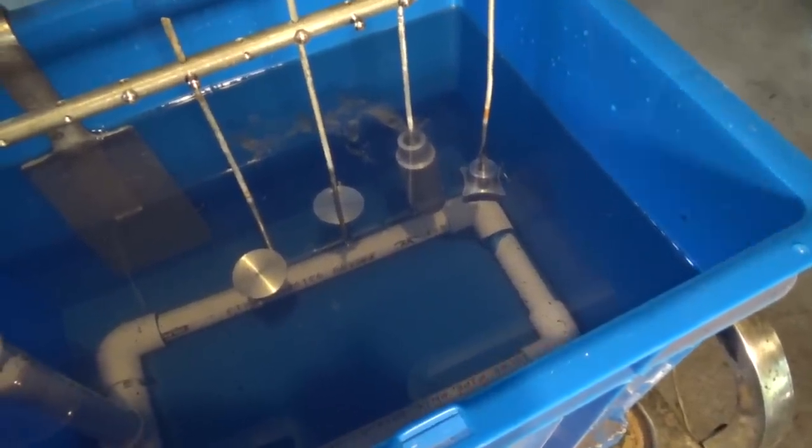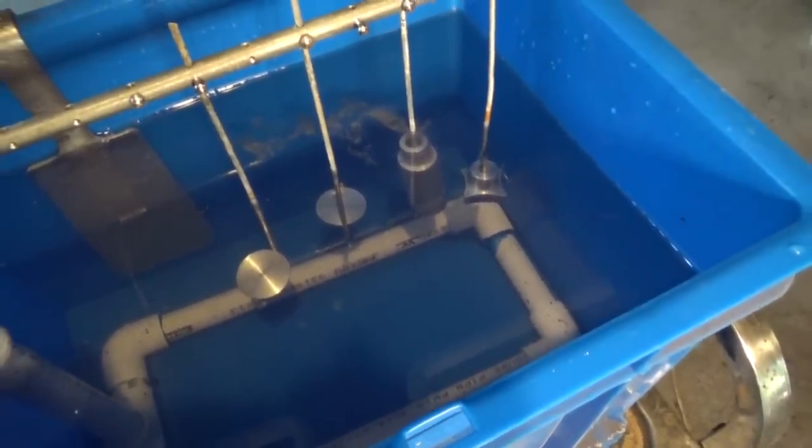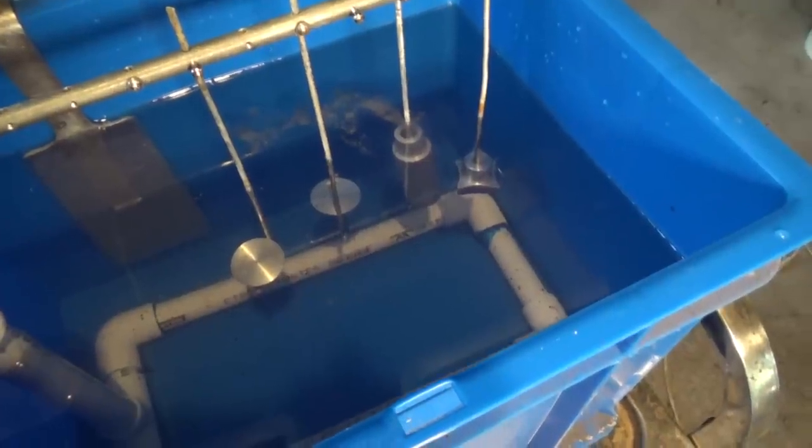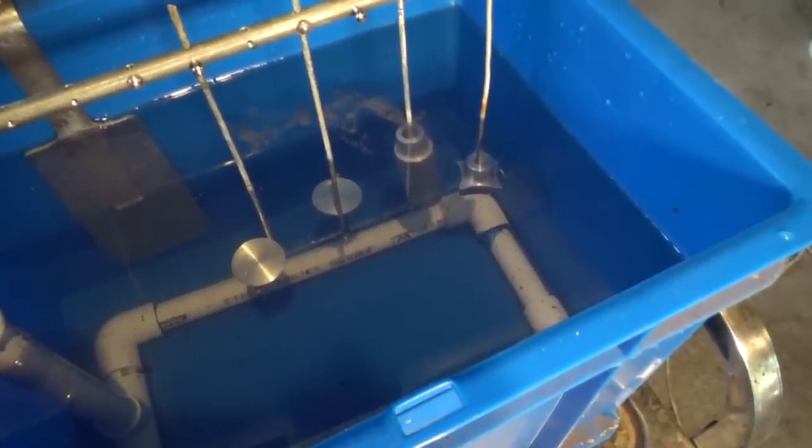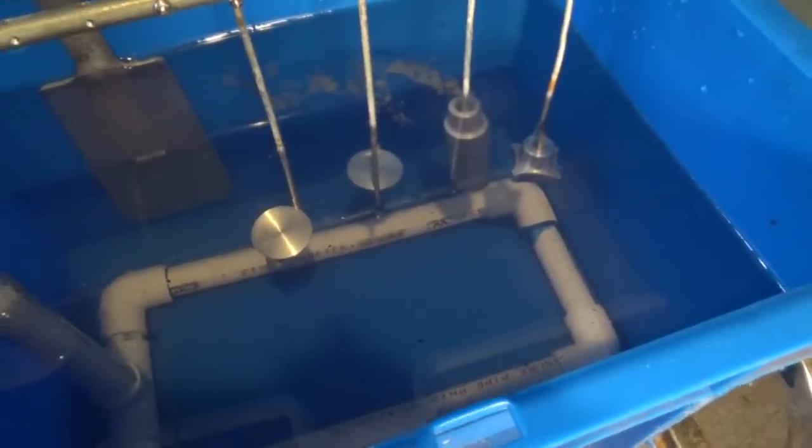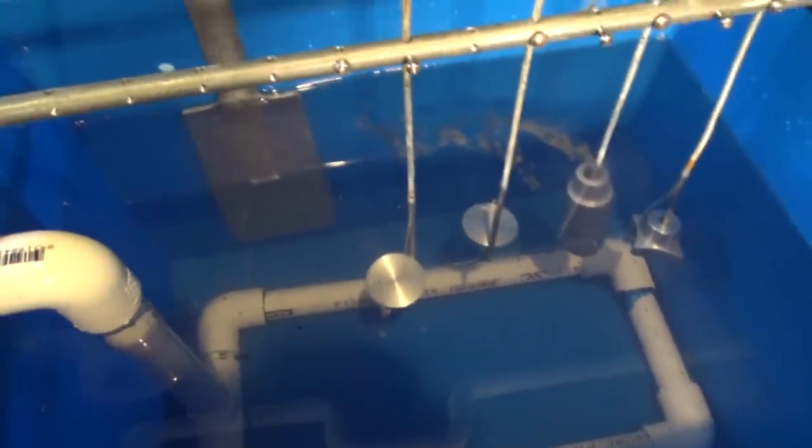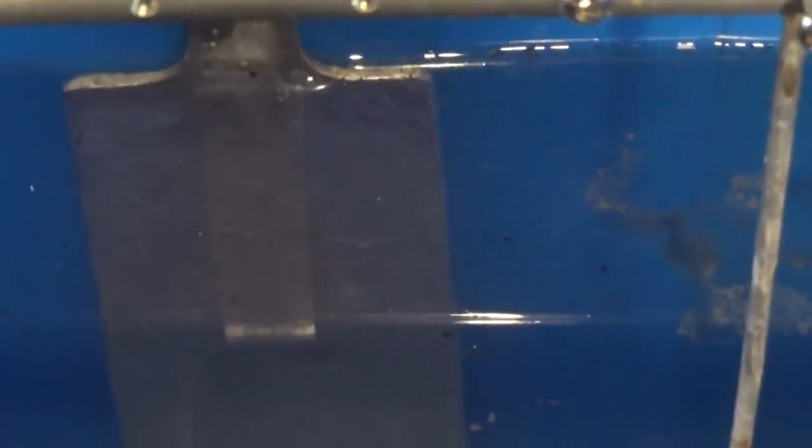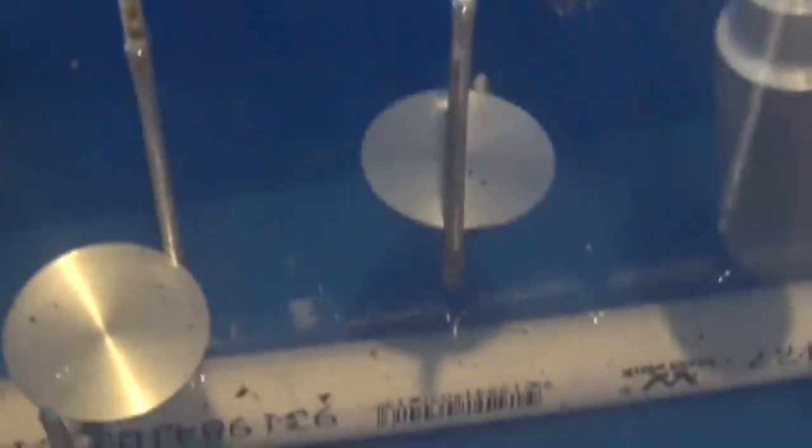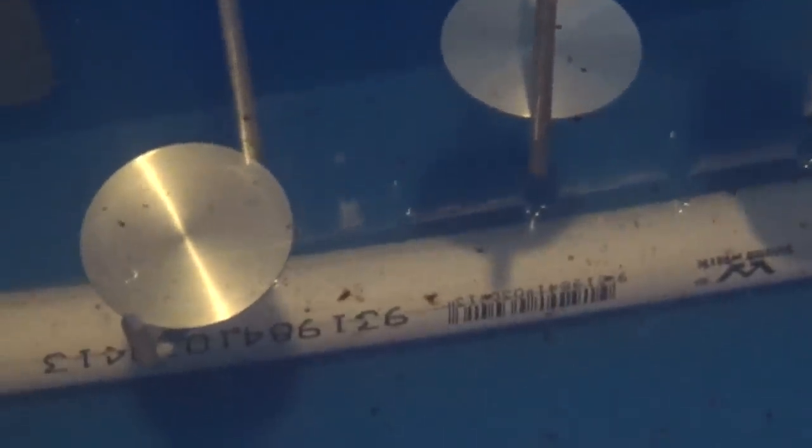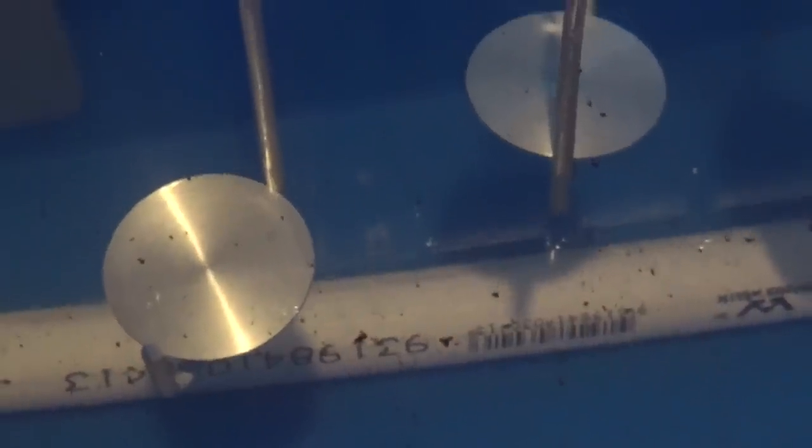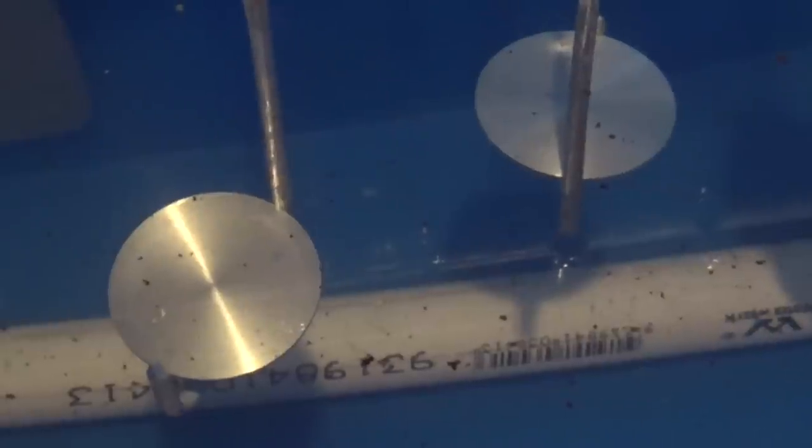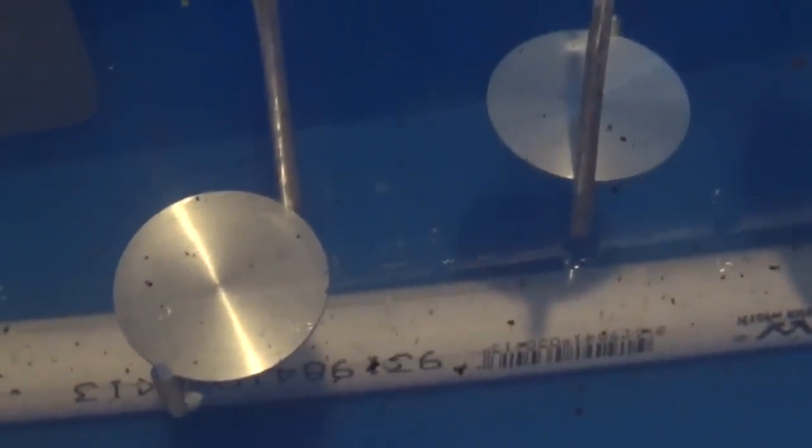What I tend to do is just set the voltage to 15 volts and then just let the parts draw up to say half an amp depending on how many parts you have in there. As far as the time goes I normally leave it for an hour or two. The longer you leave it the thicker the anodised coating will be. There's really no downside to leaving it longer rather than shorter. If you're doing everything right you should see fine bubbles coming off your cathodes. There's some very fine bubbles coming off from the cathodes. The aluminium parts should be showing some fine bubbles as well but not as much as the cathodes. Okay let's let this go now. We'll come back in about an hour and check them.